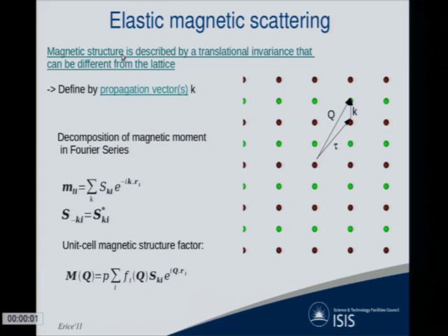The difference between structural determination and magnetic structural determination is that usually we know where the magnetic atoms are, because we know what's happening in the paramagnetic phase. So this phase itself is already known. The problem is not so much to determine the phase, it's to determine the amplitude, which is the reverse problem of what you do usually in conventional structural analysis.